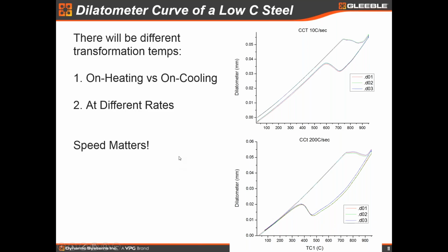And again, that's based on that nucleation rate that I talked about, and the fact that you need a little more undercooling the faster you go to kick off that reaction. So speed does matter, and that's why some of the Gleeble features are very important when you're doing fast dilatometry for fast heating and cooling for things like, say, welding or other applications where you have rapid heating and cooling rates.